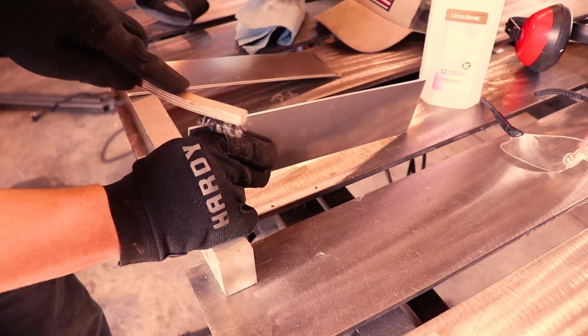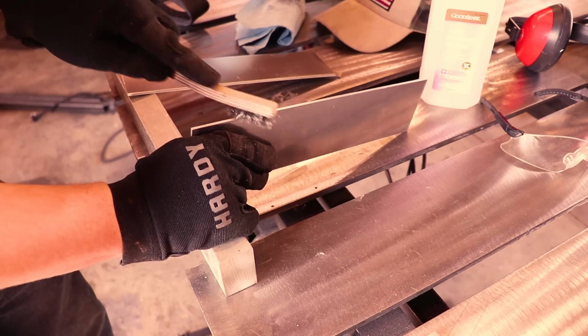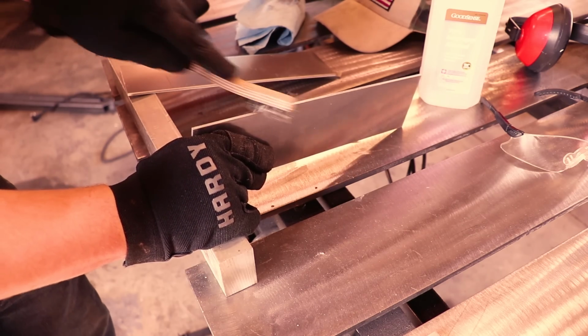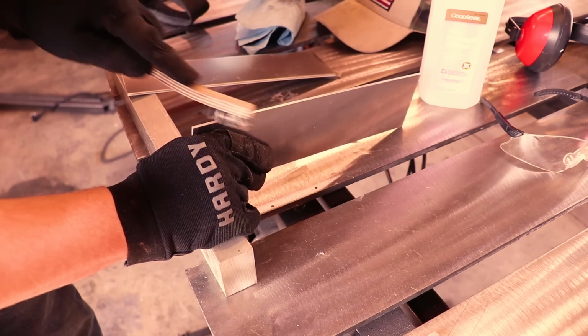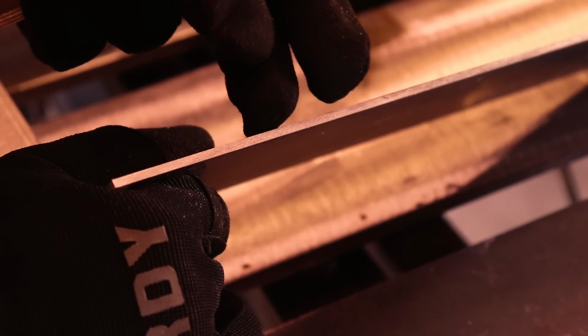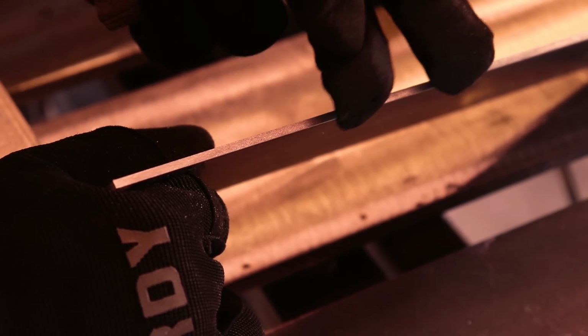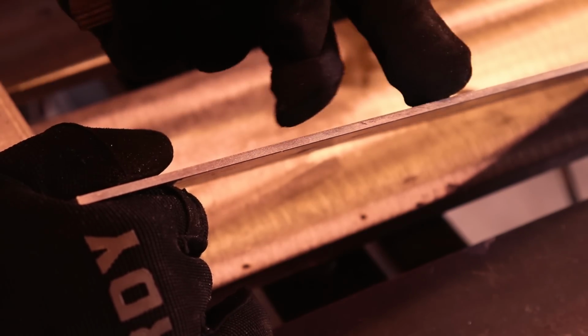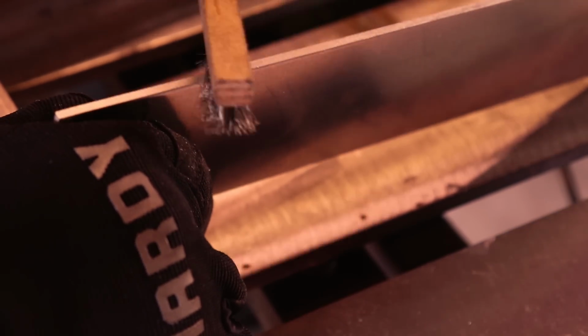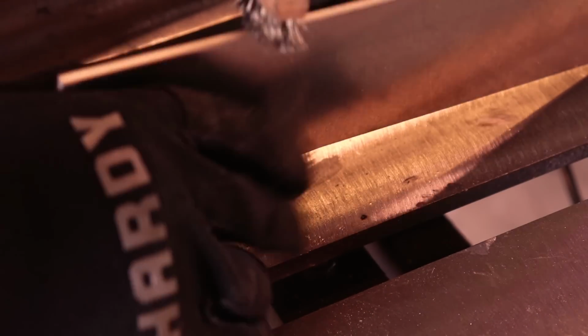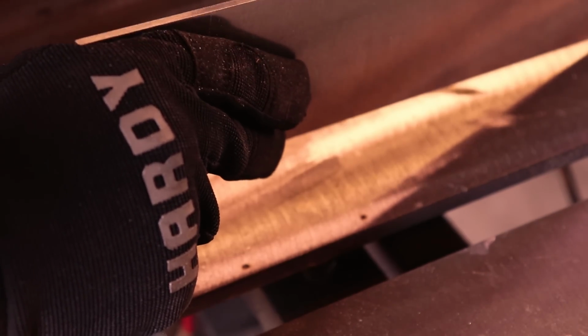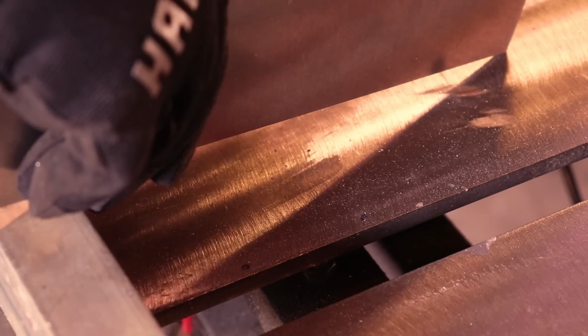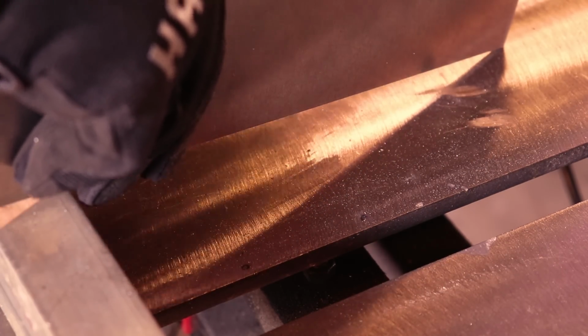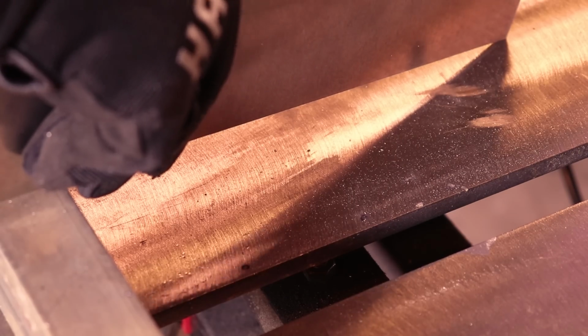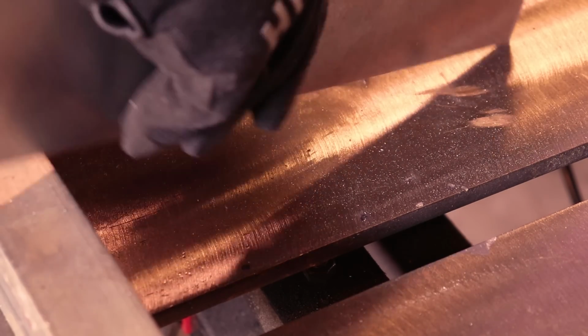Now I usually start up on edge like this, and I'm going like a side-by-side motion, kind of like I did with the file, and you can watch. Let's see if you can see. You can see the color difference here versus where I haven't got it, and that's one way to tell that you've knocked off that oxide layer. Makes it real smooth when you're welding it. So the more cleaning you do, the smoother your weld is, the easier it is to weld, the cleaner it looks, and smoother too.